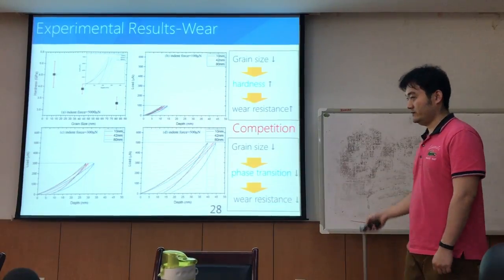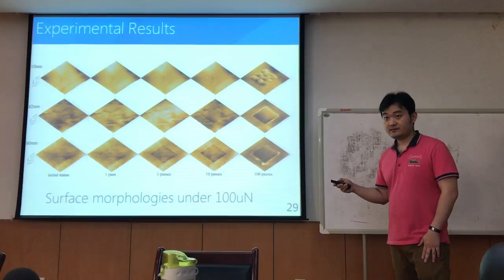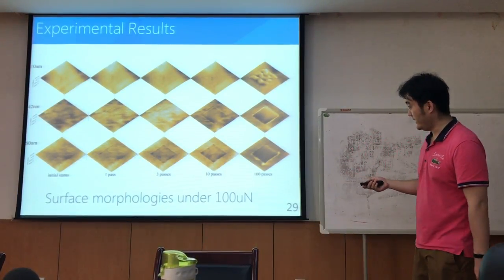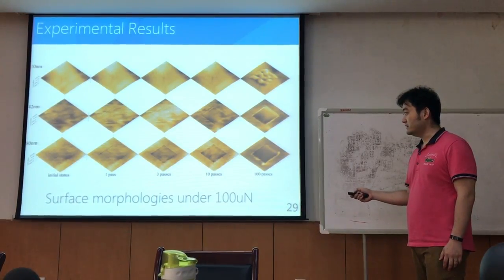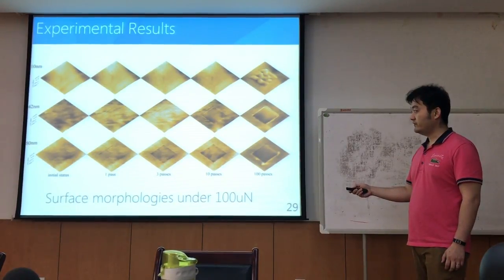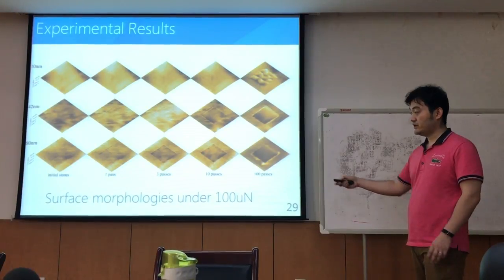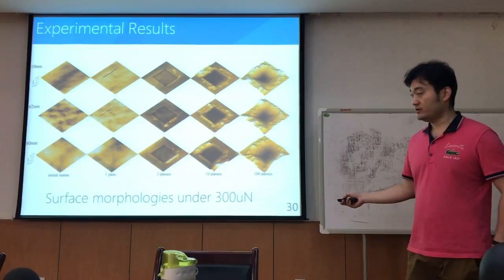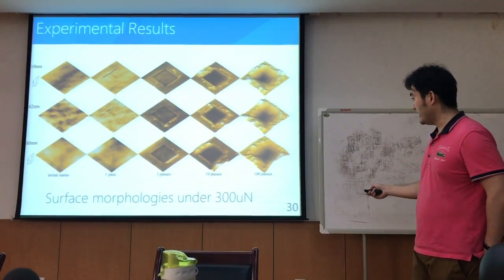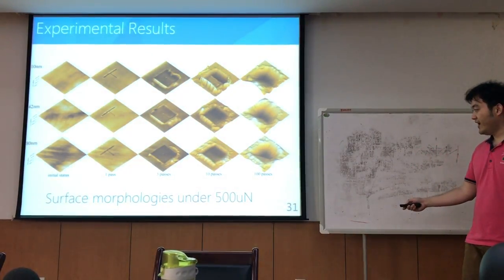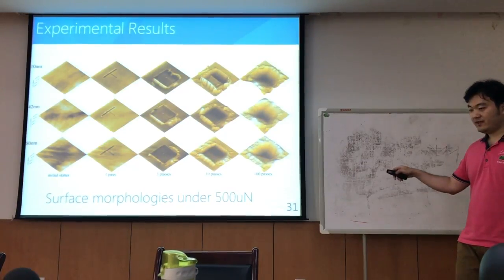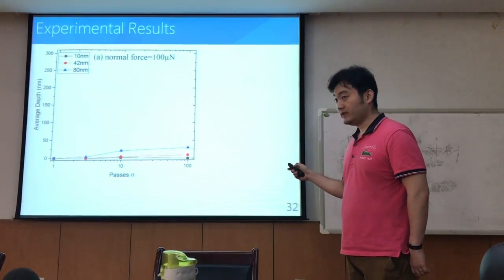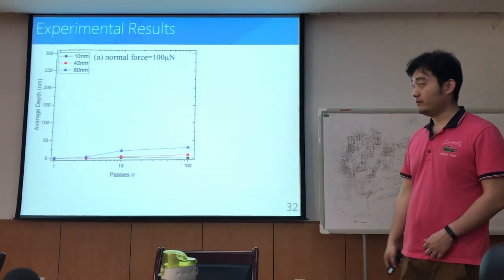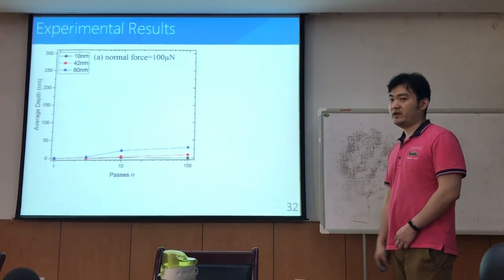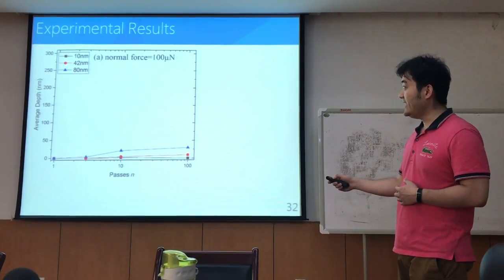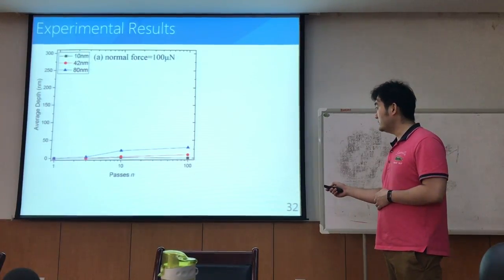So what are the results of this competition? Okay, we've done a set of tests under different force levels. Okay, first, under 100 micronewton, the surface morphology under different pass numbers is shown here. Okay, and these are the surface morphologies under 300 micronewton from 1 pass to 100 passes. And these are the surface morphologies under 500 micronewton. Okay. After analysis, we see that under 100 micronewton, the 10 nanometer grain size specimen has the best wear resistance behavior. Okay. However, the 80 nanometer grain size specimen performs worse.